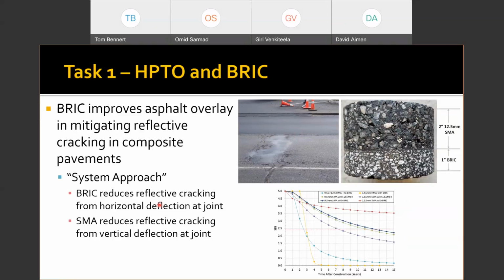So what we've done through research is verify and validate what we call a system approach, where we use a 3-inch overlay over top of these composite type pavements, using 1 inch of the bituminous-rich intermediate course on the bottom and 2 inches of an SMA over top of that. And what we have found is that by using this approach, we can improve the life of the composite pavements by over 8 years. In some cases, looking at some of the pavement sections, we've had to extrapolate that data out even further because the performance has been so good, we haven't seen deterioration.